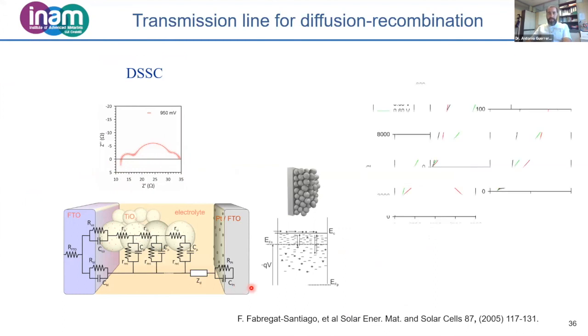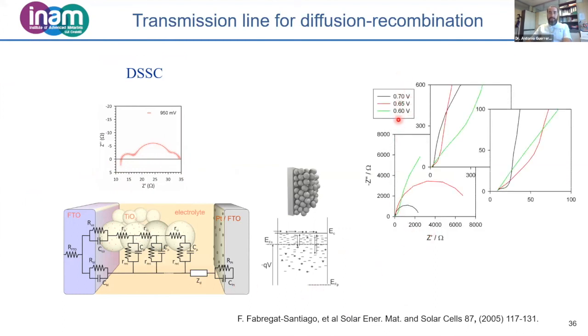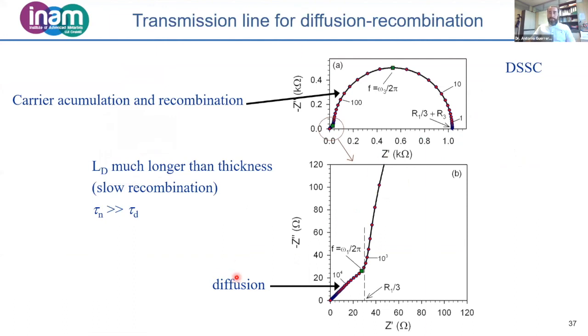This was the general equivalent circuit. And depending on the applied voltage, we could see 3 arcs, or we could see this 45-degree angle with this type of vertical line. And I need to tell you that this is the typical signature of diffusion of carriers inside a semiconductor. So the theory was well developed. And in this case, the diffusion, as I mentioned, is observed as a 45-degree angle. There is a kink in this curve, and then there is a vertical increase in the capacitance. The imaginary part of the impedance is increasing almost indefinitely.